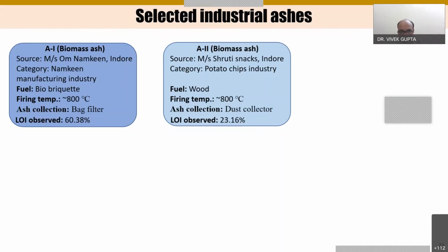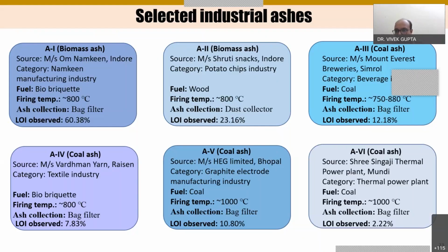You can easily compare how, due to the variation of the fuel, the characteristics of the ash differ from one industry to another. Then we also took coal-based ashes from three different industries: one from a beverage industry, one from a textile industry, and another from a graphite electrode manufacturing industry. The LOI varies from 7.83% to 12.18%. Then we also considered, to compare these industrial ashes with thermal power plant ash, one ash from the Sri Singaji thermal power plant, Mundi, where the LOI was observed as 2.22%.